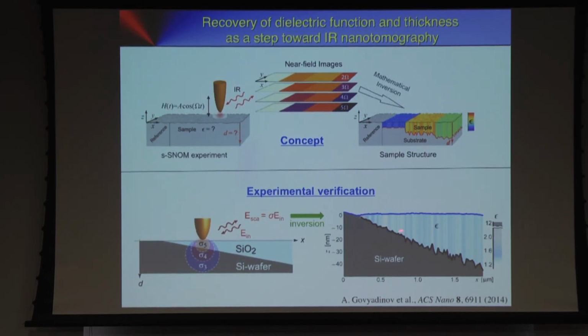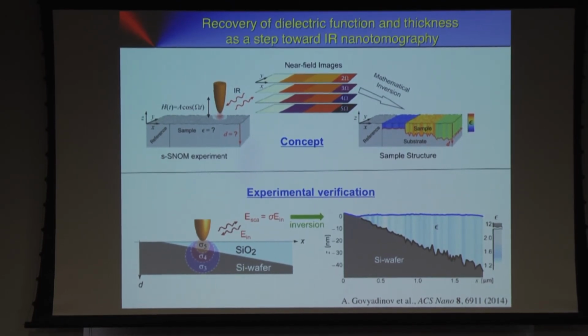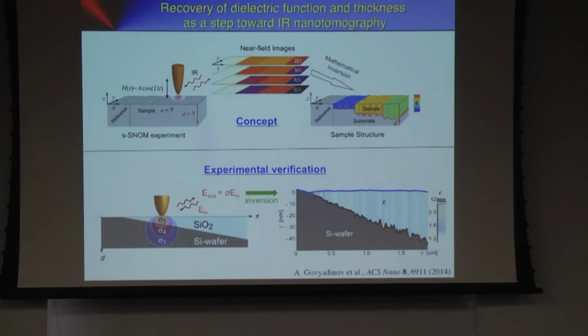That's a cross-section. That's the AFM signal. This is the permittivity that we reconstructed, the color here. It codes for refractive index or dielectric function. And this line here, that's the interface. And that took us a long time, this specific sample. This is not something that I would sell as tomography yet. It will take many, many years, and many more people need to work on it. But in principle, the possibility is there.